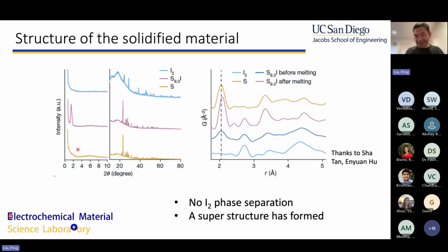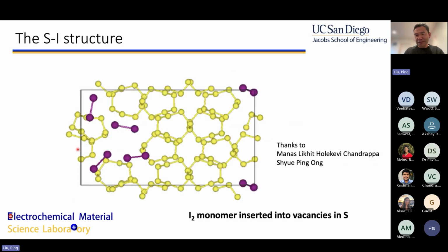So what is this material? The structural model is, if you take certain sulfur elements out and create a defect, you can put an I2 monomer into there. In case you didn't realize, iodine has precisely 4 times the atomic mass of sulfur. Sulfur is 32, iodine is 128. So exactly 4 times. So if you put in one I2, you can take one S8 out. We think that's the material we have made.